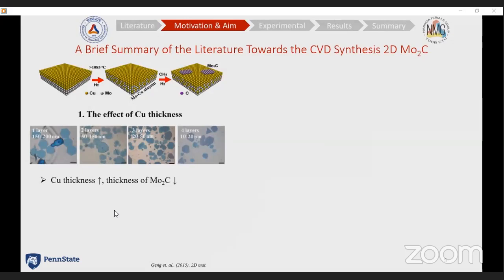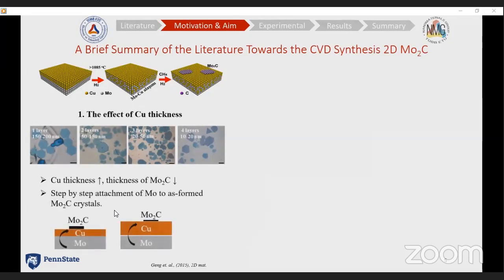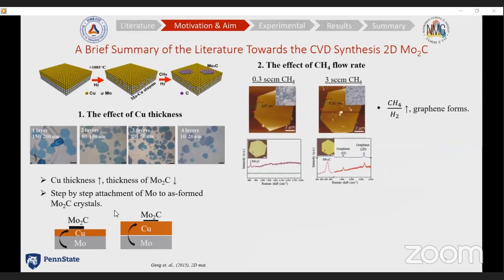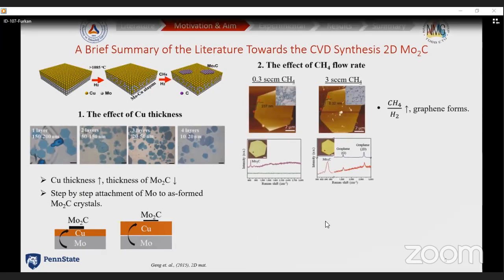So in a study, they increased the copper thickness, and then they observed a decrease in the molybdenum carbide crystal thickness. This is because by increasing the copper thickness, molybdenum species take their time to attach to the as-formed molybdenum carbide crystal, and therefore you can grow thermodynamically stable crystals with thinner features. And then the second parameter is the methane flow rate, which is the carbon precursor.